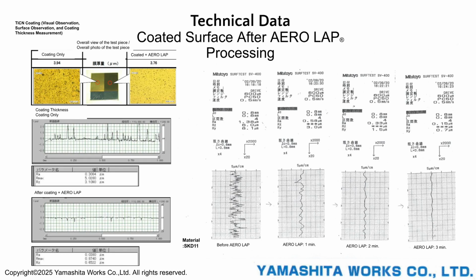On the surface without Aero Lap processing, the TiCN (titanium carbonitride) thickness is 3.94 micrometers. On the polished surface, it is 3.76 micrometers, a difference of 0.18 micrometers. From this result, we can see that the coating is not excessively removed by Aero Lap.